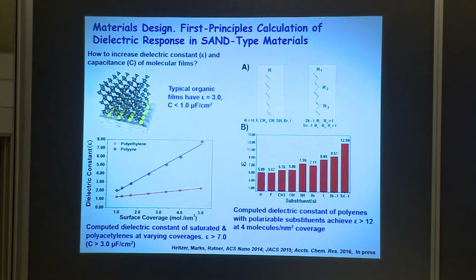And just to give you some little bits and pieces, here's a polyacetylene type structure, and here's polyethylene, and this is surface coverage and dielectric constant. And if you put on polarized, I'm sorry, we lost a bond somehow, there's one there which shouldn't be there. But if you take a polyacetylene and just put on large polarizable iodine atoms, you can get some really high computed dielectric constants. And so 12 is pretty good.